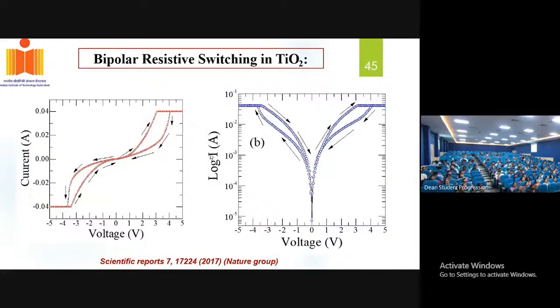Here we were able to get the set switching and the reset switching at two different polarities of the voltage. This is the set switching and this is the reset switching. Going from high resistance to low resistance state and going from low resistance to high resistance state happen at two different polarities of the voltage. So that is why I call it a bipolar resistive switching system. It is not unipolar.